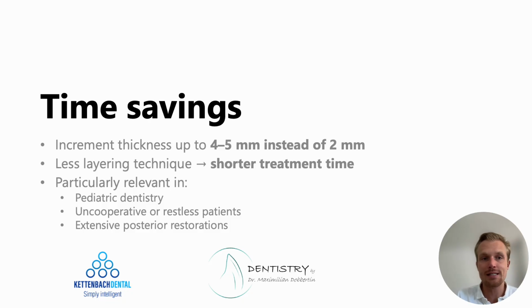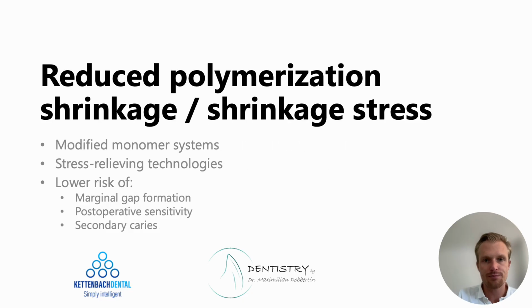Particularly relevant is this technique within the fields of pediatric dentistry, uncooperative or restless patients, but also extensive posterior restorations. A major advantage of this whole system, the bulk fill composites, is the reduced polymerization shrinkage, and with that a reduced shrinkage stress. Using modified monomer systems within those bulk fill composites enables us to fill larger cavities at the